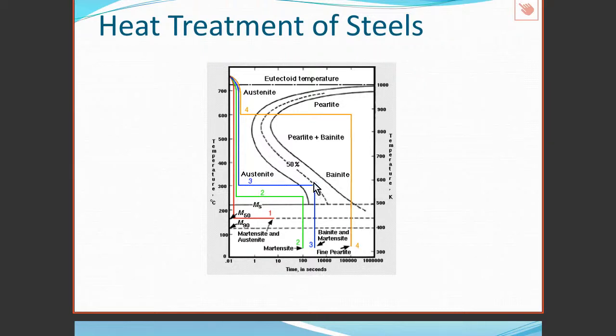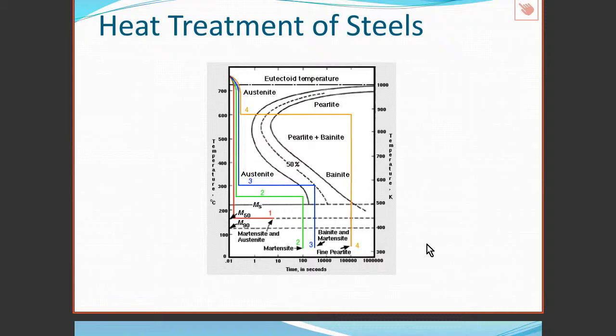The black lines on the graph form what is known as the time-temperature transformation curve. If measurements were made through continuous cooling — taking the material up to a certain temperature and allowing it to cool rather than keeping it at a certain temperature — that is a different kind of curve called a continuous cooling transformation curve. The curves are very similar in appearance and interpretation, but the actual shape differs between continuously cooling and isothermal transformation.